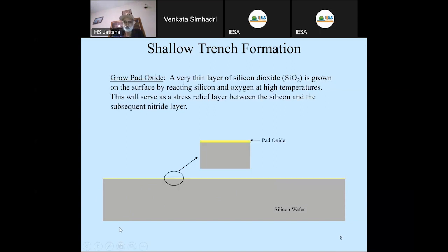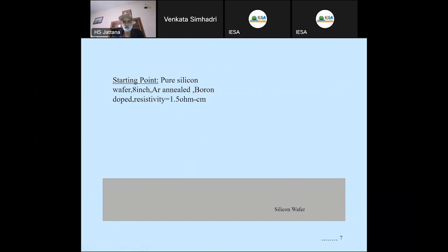So we took the wafer, and this is the wafer we have taken, 1.0 to 1.5 ohm centimeter resistivity. It's an 8-inch, it's an argon annealed, it's a boron doped wafer. Boron doped means P sub. Again, you can have P sub, you can have N sub. There are positive and negative both of these, but 80% of the time, normally boron doped wafers are used.